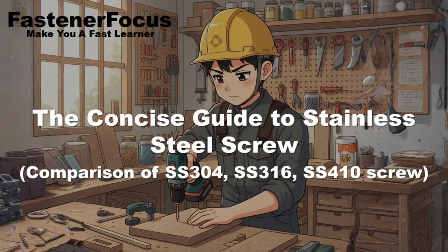hydrogen embrittlement, or HE. How does hydrogen get into the screw in the first place, and why does it matter so much? Well, hydrogen embrittlement occurs when atomic hydrogen, a byproduct of processes like acid cleaning, pickling, or, most commonly, electroplating like zinc or cadmium plating, is absorbed into the metal structure. In a high-strength, hard, crystalline structure like fully hardened 410 martensite, these tiny hydrogen atoms diffuse to points of high internal stress, and they essentially weaken the bonds between the steel grains.